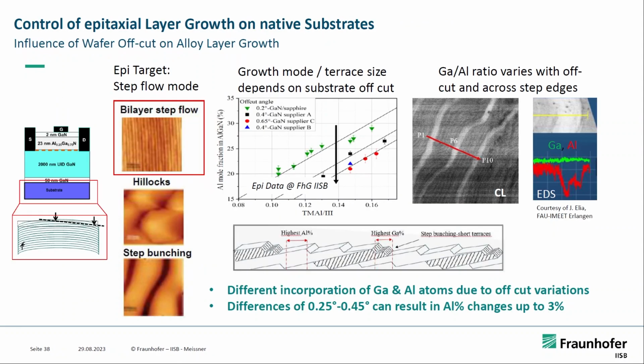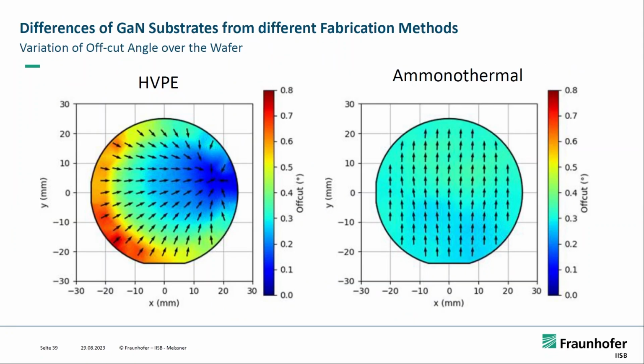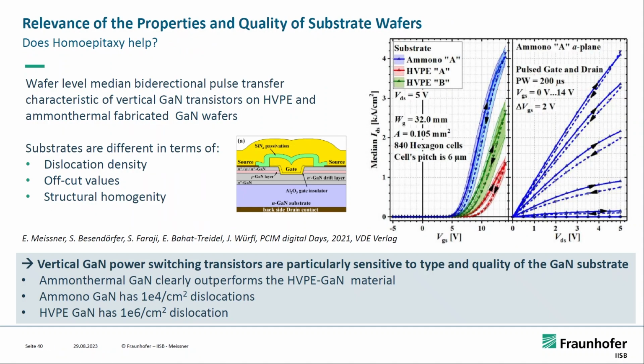So the issue that we've seen before with this offcut and the uneven incorporation of the atoms into the alloy barrier layers, this is less of an issue in the ammonothermal material. And this is where we think, as you have seen before, where these differences may come from.